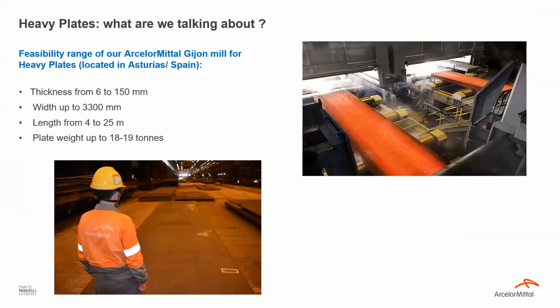So the ArcelorMittal production mill for heavy steel plates is actually located in Spain, in Gijón. This is in northwest of Spain. The plates feasibility range of this mill in Gijón goes from thicknesses starting at 6 millimeter up to 150 millimeter thick. The width goes up to 3.3 meters. Length up to 25 meters, and the plate weights can be produced up to 19 tons, more or less. So this is a real competitive advantage since specific markets, for instance, windmill towers, require heavy plates with increased weight.